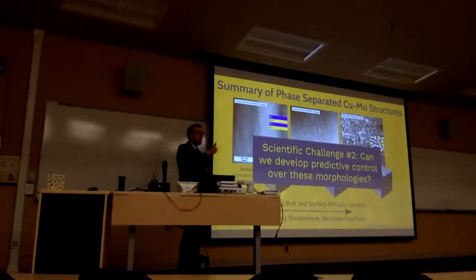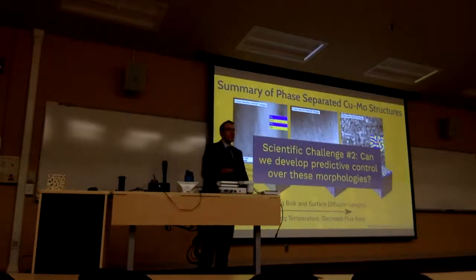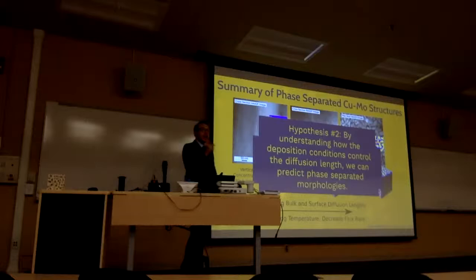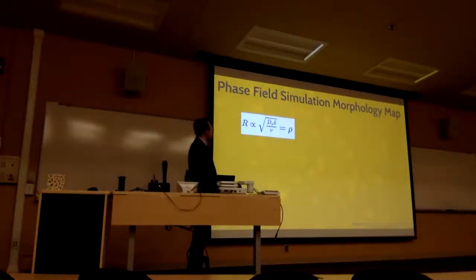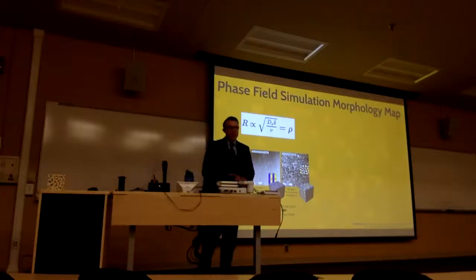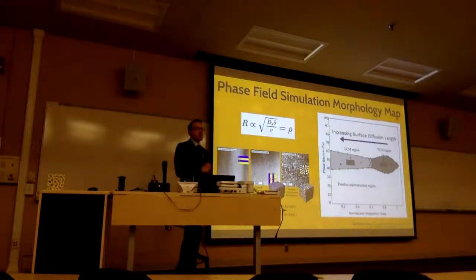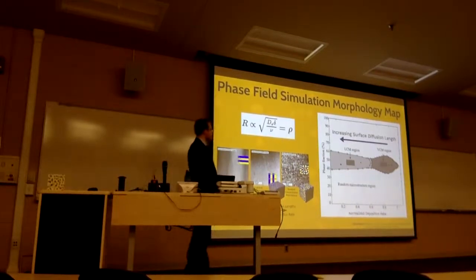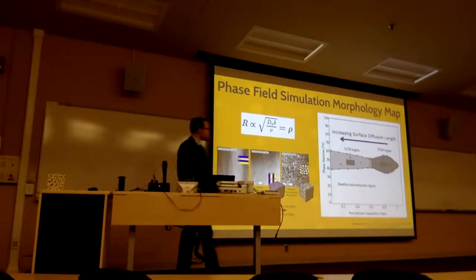And so if you come to me and want to design your material in a very specific way, the next challenge we saw is, can we develop some sort of predictive control over these morphologies? Could I tell you the deposition conditions you need to design your material in a very specific way? So our hypothesis is that by understanding how the deposition conditions play into that diffusion length, we can start to predict these phase-separated morphologies. So starting with this equation here, and matching it up with our empirical results, the Yunzhi Wang group at Ohio State actually put forth a morphology map based on their phase field simulation that describes the phase fraction of the material against a normalized deposition rate. Now don't let that confuse you, that's just the inverse of the surface diffusion length proposed by Dr. Betzman's group. So our material actually has equal amounts of the two materials, so 50% fraction. And you can see that depending on the surface diffusion length, you can actually change the direction of phase separation using those deposition conditions.